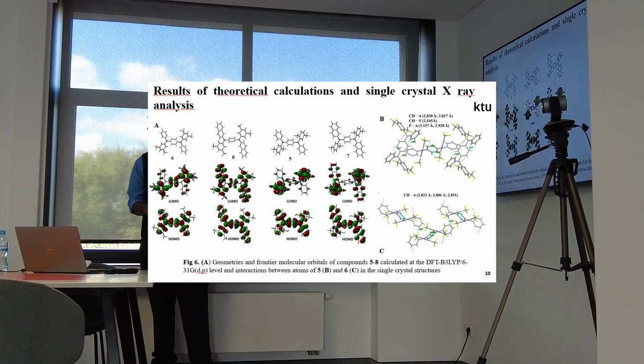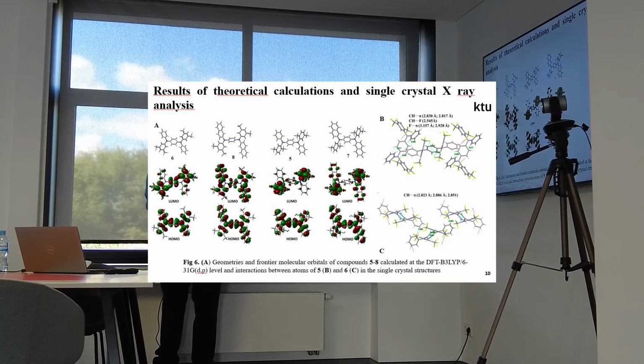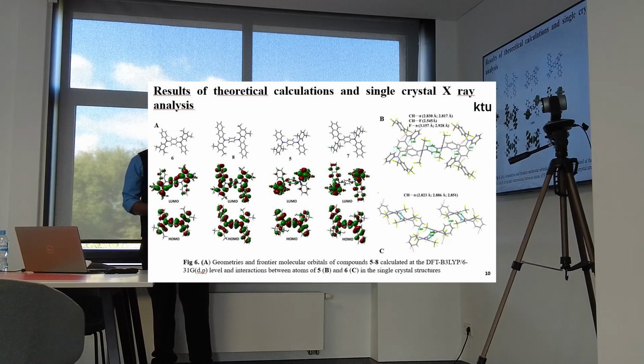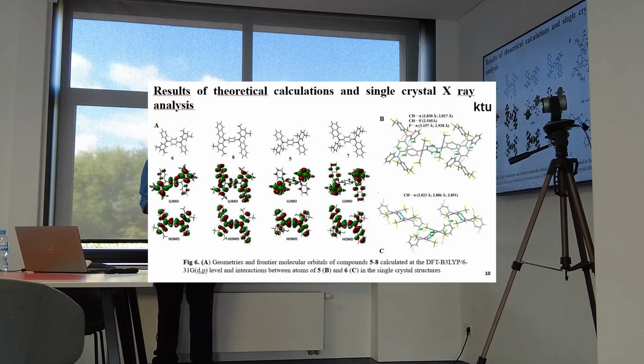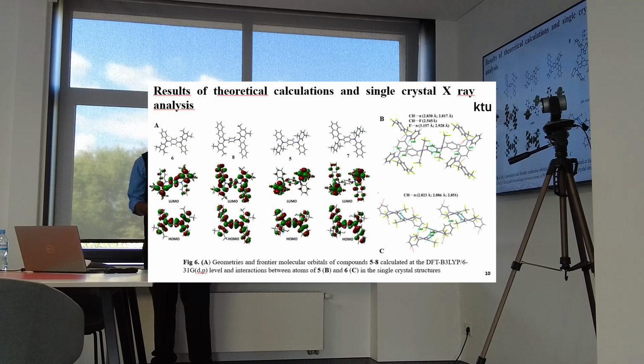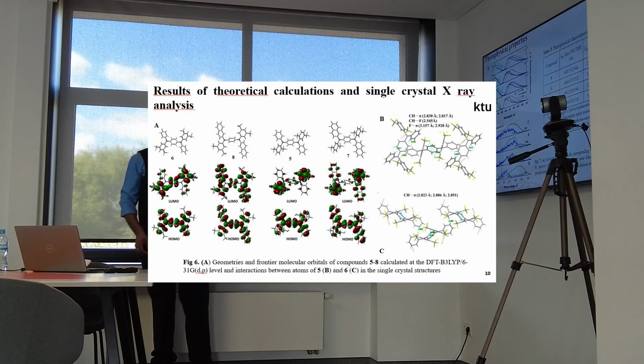compounds are distributed over the molecular backbone of the materials, and the lowest unoccupied molecular orbital of compounds 5 and 7 are localized to fluorine atoms, however for compounds 6 and 8 they are distributed over the molecular backbone. And the single crystal analysis revealed that compound 5 displayed inter and intramolecular interactions with carbon to pi, carbon to fluorine and fluorine to hydrogen interactions. However, compound 6 with meta-substituted fluorine atoms displayed only inter and intramolecular interactions.